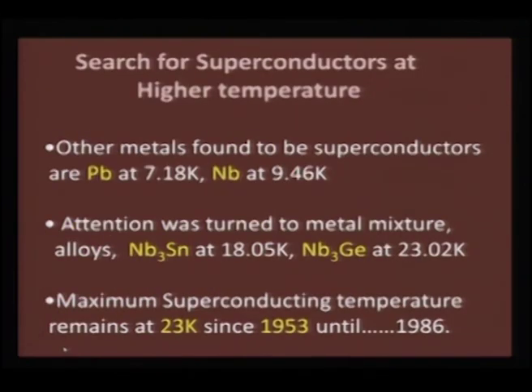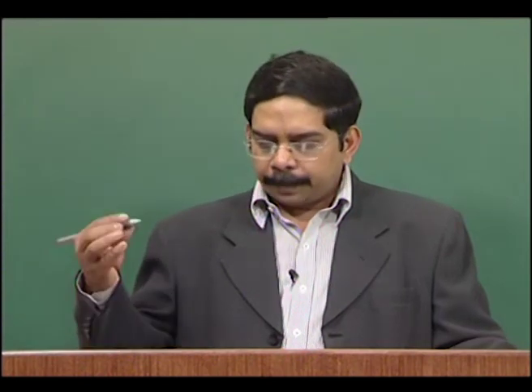The search for superconductors at higher temperature has been the focus since this discovery. Other metals found to be superconductors are lead at 7.1 K, niobium at 9.46 K, and then came the A15 type metals or alloys, such as niobium stannide and niobium germanide. All these show superconductivity up to around 23 K, and the maximum superconducting temperature achieved up to 1953 was only 23 K. Nevertheless, with this finding several useful applications have happened over the years, and these metals are malleable, therefore you can make them into any shape.